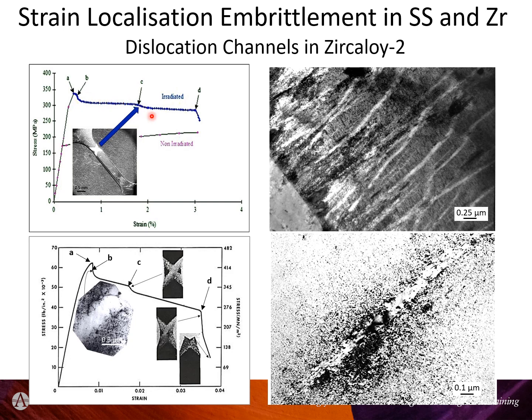And if we see a second drop, that's understandable, because the first load drop corresponds with the initiation of one slip system, which, according to the Schmid factor, may just be the lowest of all possibilities. And the second load drop occurs because when the tensile specimen is deforming and slipping, it loses its continuity with the load line.